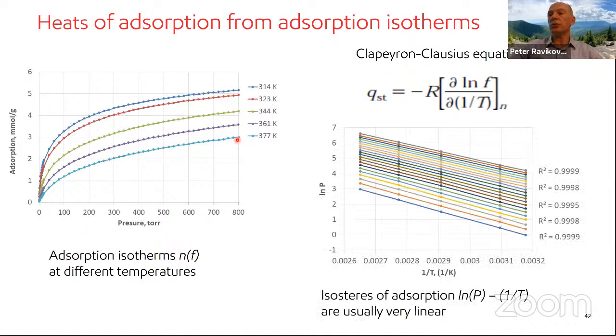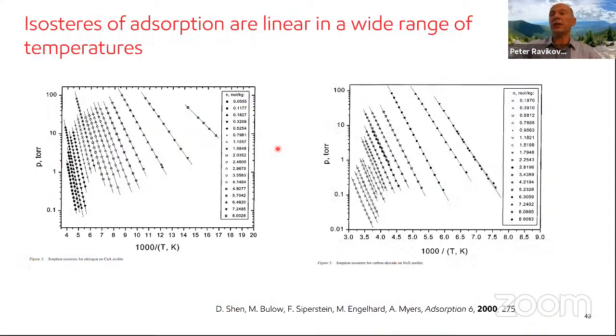If you use the Clapeyron-Clausius equation and you plot the so-called isosteres of adsorption, and you try to do regression on those points, it is very typical to have 3, if not 4 nines. So they are really linear. And if you do not see 3 nines or 2 nines, you should start worrying about the quality of your experimental data. This is a fact which has been shown many times. For example, this is a much wider temperature range, from Martin Bülow, who developed the isosteric method to calculate the heats of adsorption. And so these are really linear isosteres in different systems, different molecules.